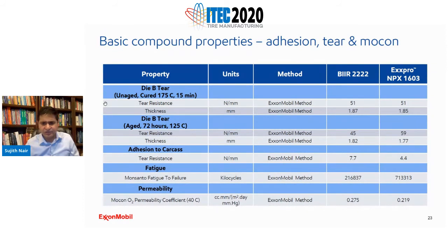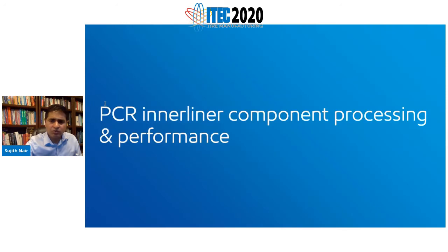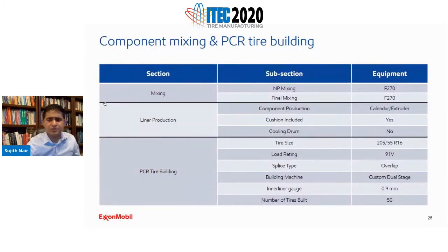Similarly, you can see that the fatigue to failure of X-Pro is around twice that of bromobutyl, and the permeability is around 20% lower. So basically, almost all component properties are equal to that of bromobutyl, and obviously you have some advantages with respect to permeability, green strength, fatigue to failure, and composition.